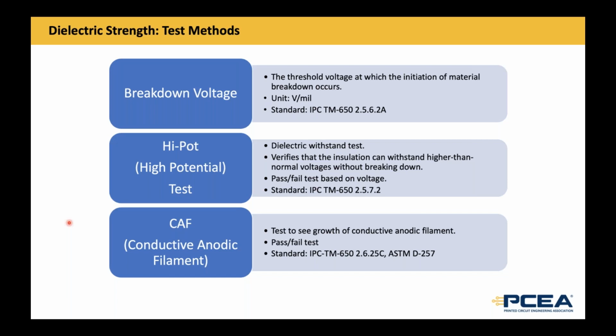But that never stops any OEM from specifying a different value for a different application. CAF testing, for instance, it's the Wild West. It goes everywhere from 5 volts to 5,000 volts, depending on the application. And temperature and humidity can be from benign room temperature and humidity all the way up to 85% humidity at 85 or higher temperature, and any combination of all those three things. The reason is that the density requirements in the circuit board affect CAF. The thickness of the circuit board affects CAF. The hole size affects CAF. And the fabricator's cleanliness affects CAF. So it's a pretty complicated thing to try to cover in a standard specification.